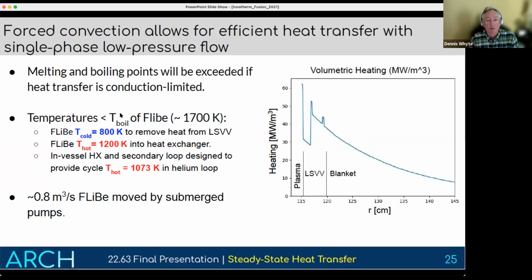So in the end, we came up with a solution to this. It's really tough. You can see the kinds of levels of heating that we're talking about in terms of megawatts per cubic meter, from the plasma through the LSVV into the blanket. Here's that characteristic e-folding length that I talked about before of around 20 centimeters. And you can see the upfront concentrations of all this power are now pushing into 40 and 50 megawatts per cubic meter. So in the end, we were forced to allow the temperature of the flibe to increase substantially, which is okay in general, but it was bringing in other challenges like corrosion control in the salt, but I'm not going to get into that. And in the end, we figured out we could make this work with flibe essentially being pumped around globally at about 0.8 cubic meters per second by submerged pumps.